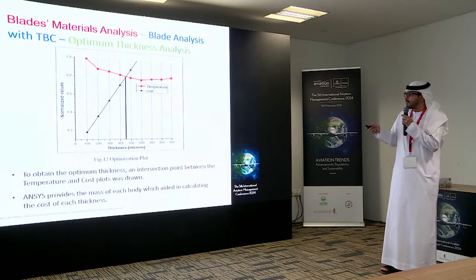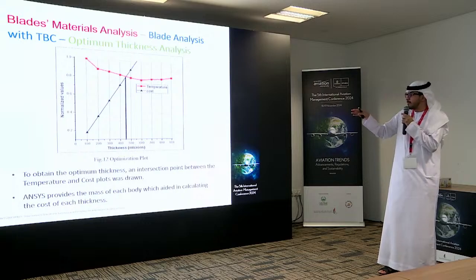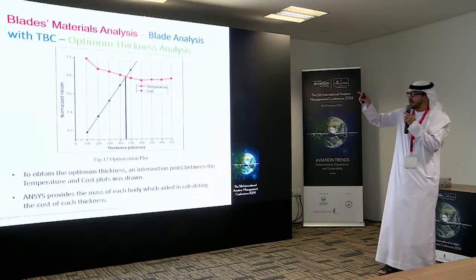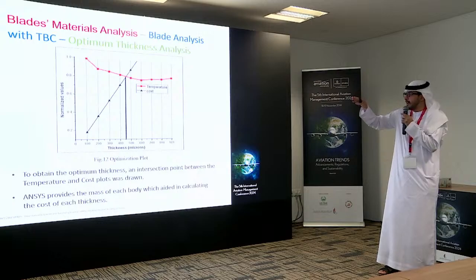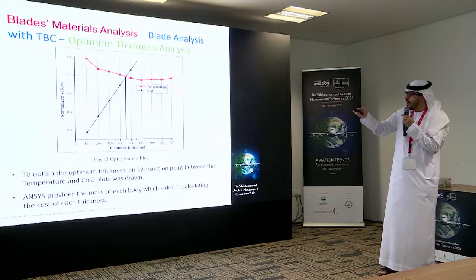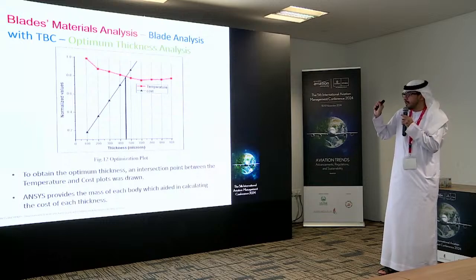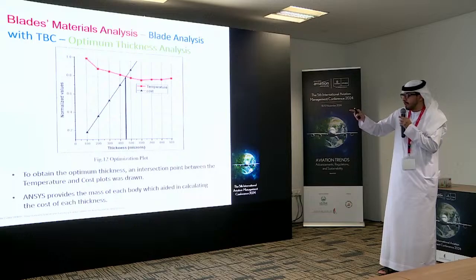In this plot, it shows you that for various thicknesses from 100 up to 900, the temperature will start to decrease, and then it will slightly increase at the end. However, there is the black plot, which shows you the cost. Now, in order to choose the optimal thickness for the coating, we made an intersection point between the cost and the temperature, and they intersect at 550 micrometers.